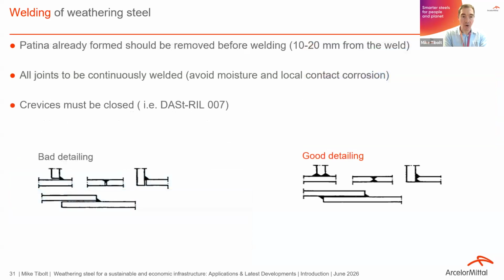You see that depending on the process of welding, you have different options that you can select for the weld metal. Also, you should the patina already formed should be removed before welding, so you should remove it 1 to 2 centimeters away from the weld. And all joints should be continuously welded to avoid spaces for crevices, which must be closed, so that you cannot have water entering by capillary effect into these spaces.